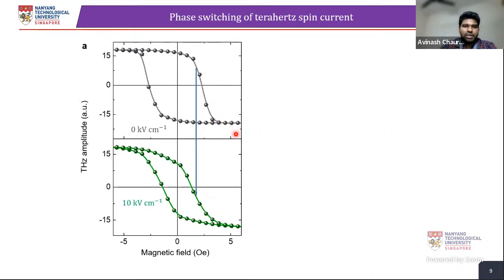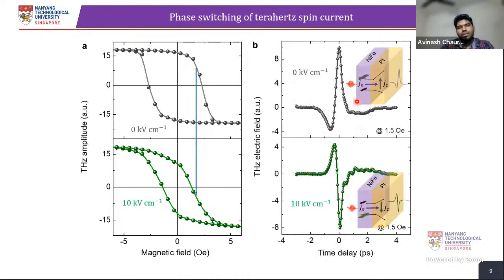So till now, I have discussed how to control the terahertz amplitude. Now I want to control the amplitude as well as phase. To control the phase, using the strain alone, it's difficult to control the switching of the terahertz pulse. For that, we need a small magnetic field. So first of all, we did the hysteresis measurement. Similar to the MH hysteresis, terahertz hysteresis also forms this kind of behavior, where we apply the magnetic field and measure the terahertz amplitude. As you see, when we apply the electric field, this hysteresis loop shifts. That means if we choose this point and apply the electric field from 0 to 10, we can see the switching in the phase of the terahertz pulse at a given magnetic field.